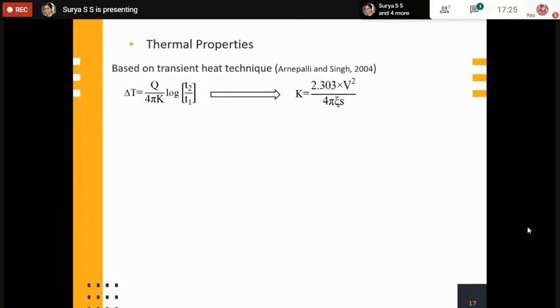So the change in temperature, that is delta T, I can connect to the thermal conductivity using this equation. From this equation, I can plot the variation of delta T with log T2 by T1, where T2 by T1 is the time. At different time intervals, if I can get the delta T value and plot a variation, I'll get a straight line because it is a straight line equation. The slope of that will give me Q by 4 pi K, where Q is the heat energy. Q, I can convert in terms of voltage or current, and then from that slope, I'll back calculate what is my thermal conductivity. So that is what I was doing.